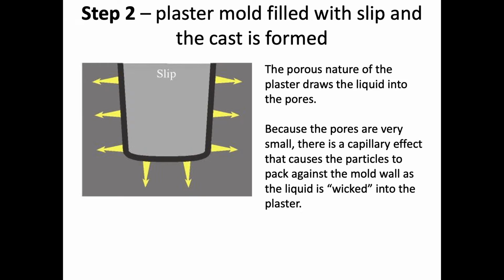So the second step is we have to fill this plaster mold with the slip. And so that's this plaster mold. Plaster is the most common material. It's very porous. The porous nature of the plaster, it has very small pores and actually acts with a capillary effect. So what that does is it draws out the liquid into the mold wall.